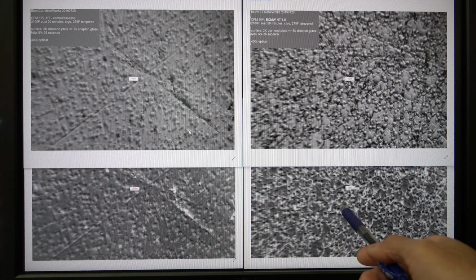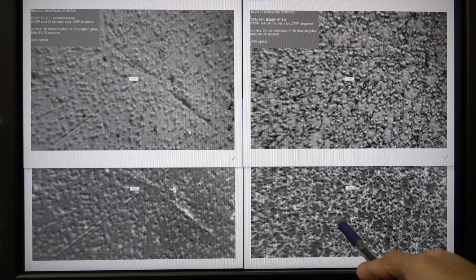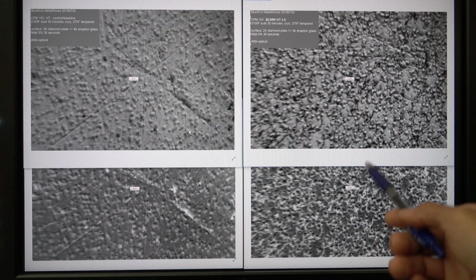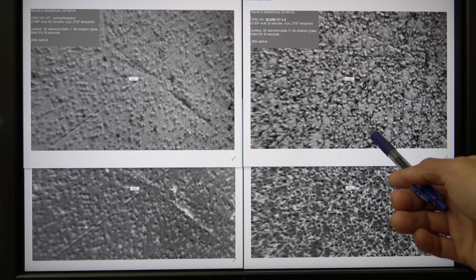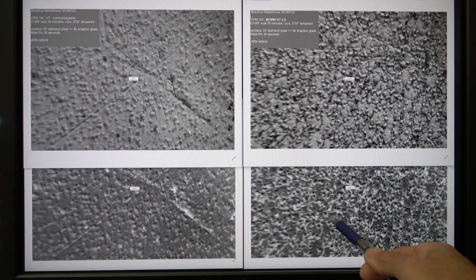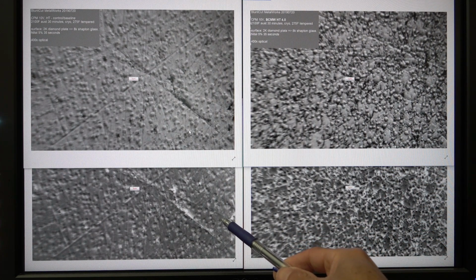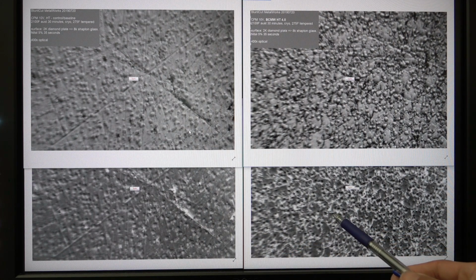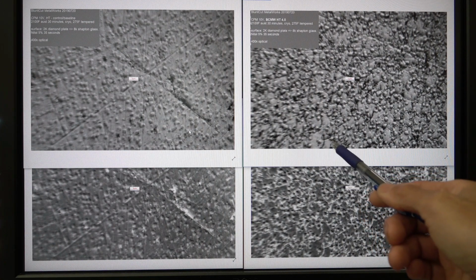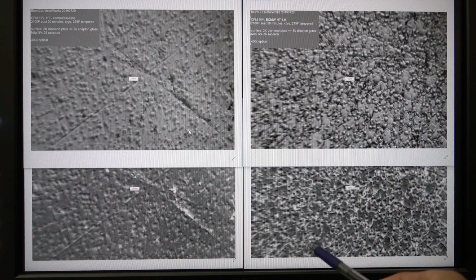And from this, if you look at this crater, you can see at least half of the carbide actually protruding, versus less than half, maybe like a third right here. And this is less than half because you can see the deep shadow into the surface here. See the black here is the matrix surface. So we have this spot and this spot right there, you can see. Anyway, so you see the depth.